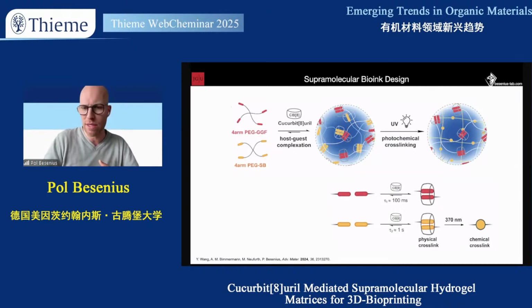And that lower handle, you can then fixate, and you go from a physical dynamic crosslink to a chemical covalent crosslink that, at least on the timescale of the typical rheological experiment, cannot be broken.